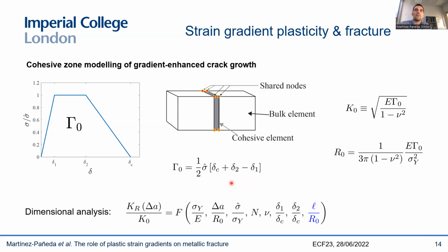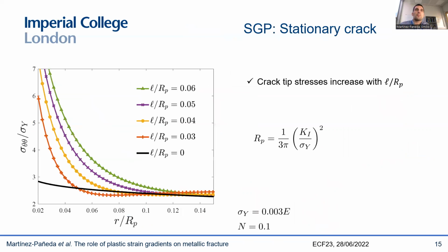And the only difference between their study and ours is that because we're using gradient plasticity, we have this additional non-dimensional set. So the ratio between the length scale that tells us how easy it is for the material to harden due to the presence of GNDs, and this R0, is what is going to change the picture, what is going to govern material behavior. So before we look into crack propagation, we again look at the stationary crack tip fields, and you can see that this ratio between the length scale and in this case the plastic zone is what governs the material behavior.